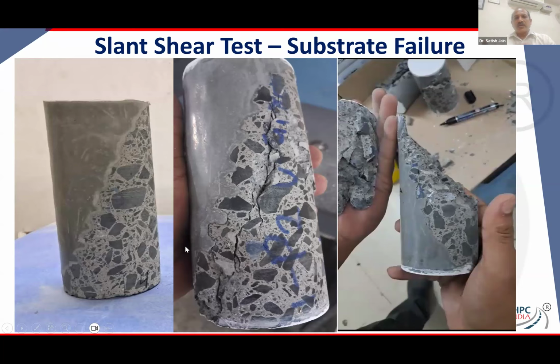So, of course, we replicated the roughening that we did on the deck onto the concrete that was done over here, to showcase that yes, bonding does happen. Really good bonding happens. In fact, as another project for those in Mumbai, you can visit a flyover at Targar, right next to the Navi Mumbai International Airport, that has just opened. One of these spans was fully strengthened with UHPC, and there is no wearing course on it. There is absolutely no wearing course on it.